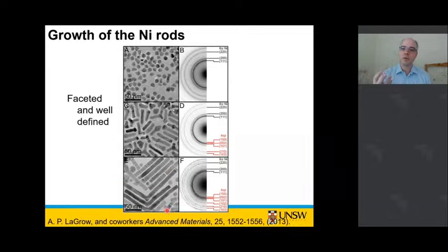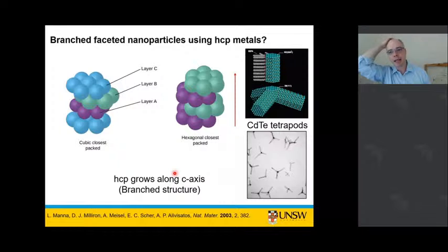And as you can see, these structures are more the structures that we're after. So we have a nice core there, but we're actually ending up with these very straight edges and straight tops, which indicates we are getting towards the kind of low index facets that we're really after. So this was all with pure nickel in a one-pot synthesis. So you're just putting in your nickel precursor and doing your reaction and seeing what you'll get. But this really gave us a clue for the mechanism that we want to chase. And this mechanism really relies on having cubic close-packed and hexagonal close-packed structures.